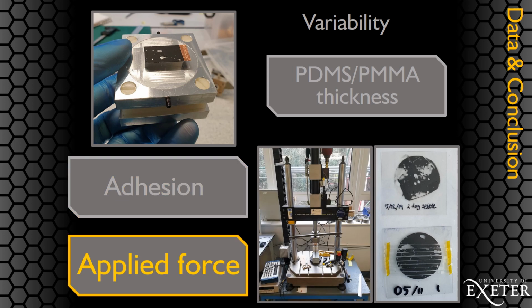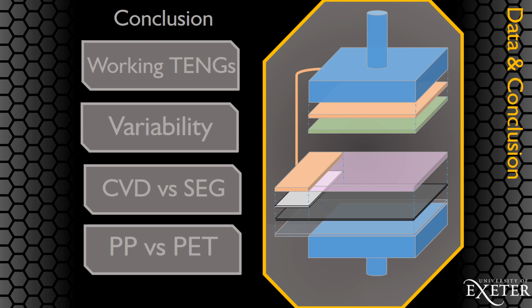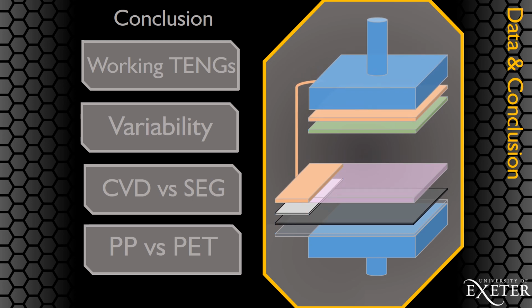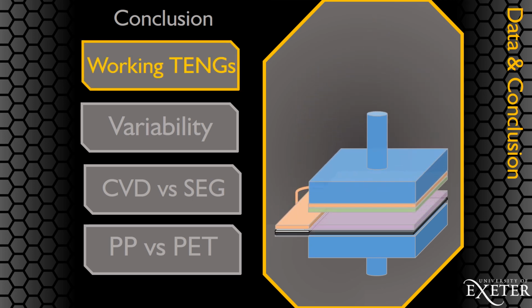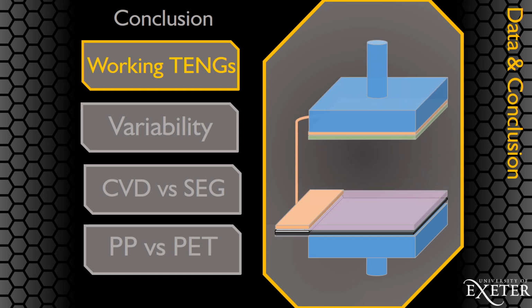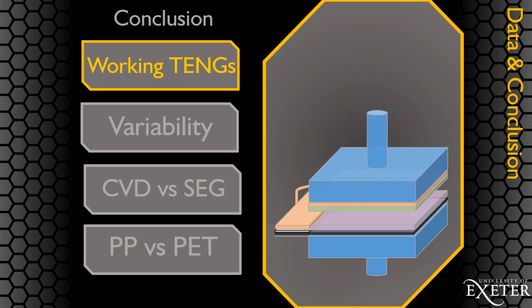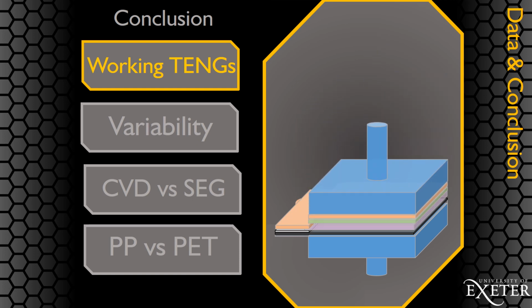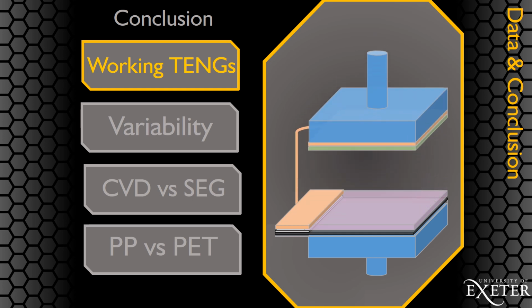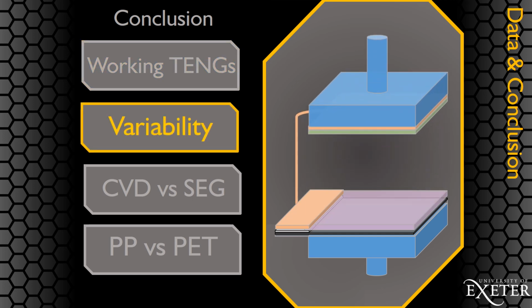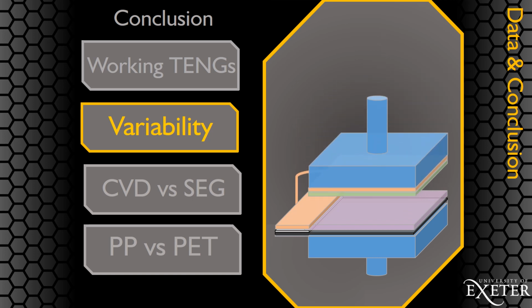Applied force is also overlooked as a variable, as programming the vertical contact machine to use the same force each time is difficult to control when samples are constantly being replaced and changed. Now, to conclude, we have achieved the goal of producing and characterizing triboelectric nanogenerators using 2 different graphene and polymer substrates. All were functional and able to provide enough charge to be considered a viable option to integrate within e-textiles. However, there were still issues present that mainly involved the device's durability and effective power.